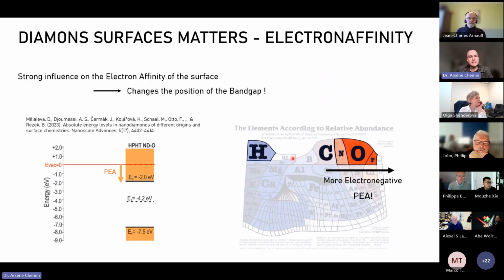So what does that mean? Well, if you consider the bandgap of a diamond, these diagrams here are extracted from a very nice article from 2023, where they compared the band positions of many different nanodiamonds. You will see that for oxygen nanodiamond, the bandgap would be much lower compared to the vacuum level. And the conduction band will be lower than the vacuum level. And this is what we mean by positive electron affinity. The way you can understand that is that if you have the surface of the diamond covered with oxygen, that pulled electrons from the crystal and is overall slightly negatively charged, if you excite electrons to the conduction band of the diamond, they will struggle to exit the surface. There will be some kind of energetic barrier to overcome. And this is the positive electron affinity.